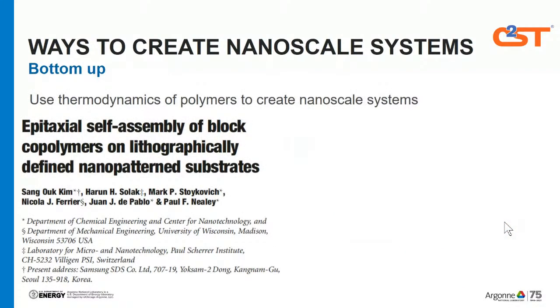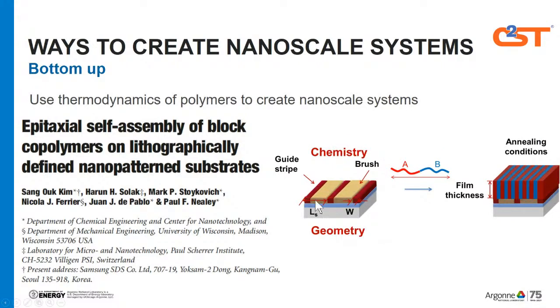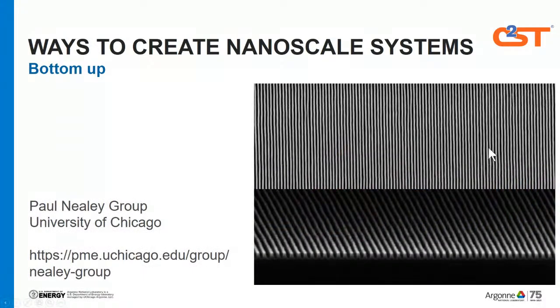Another bottom up approach that kind of bridges between bottom up and top down is the self-assembly of polymers. What you can do is create a polymer, one side hydrophobic, one side hydrophilic. And when you anneal them, you can get them to form these stripes. You can do this across a very large area because that's thermodynamically favorable. And they can do this across a whole 300 millimeter wafer, so 12-inch wafer in CMOS. So the processes that make your consumer electronics use this to help them with patterning. So not only is it bottom up, but they combine it with top down. And this is kind of a bridge between the two.